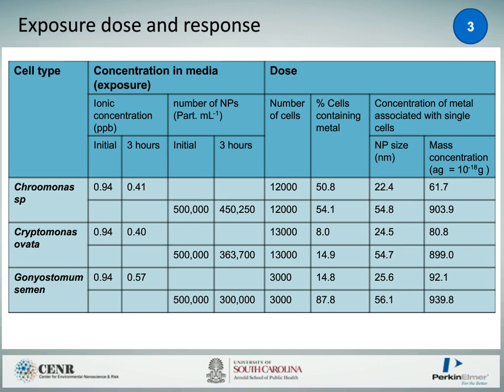And then on the right-hand side, we can now talk about dose. So you can measure your number of cells at the beginning and at a 3-hour time point, and you can say how many cells you have. And then you can say from the single cell ICP-MS data, the percentage of cells that contain metals. So you can see that the smaller cell contained around 50% for both ionic and nanoparticulate. And then when you go to the larger cell, 15% of the cells contained ionic, but 87% of the cells contained a nanoparticle of some description that was measured. So then you can actually go and look at your data. We had a nanoparticle size for each of these uptakes. So we had a 22 nanometer, or what can be considered a 22 nanometer size particle, contained within the ionic exposure for the first cell. And you can see that you have a particle size of around 55 when you expose it to nanoparticles.